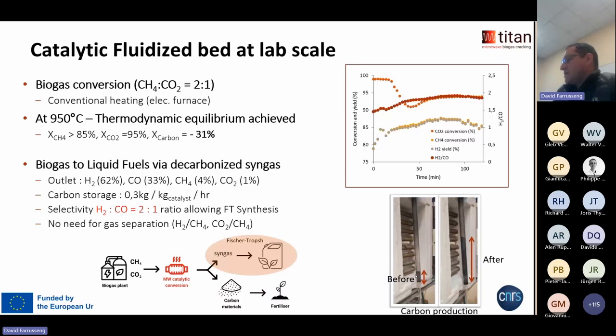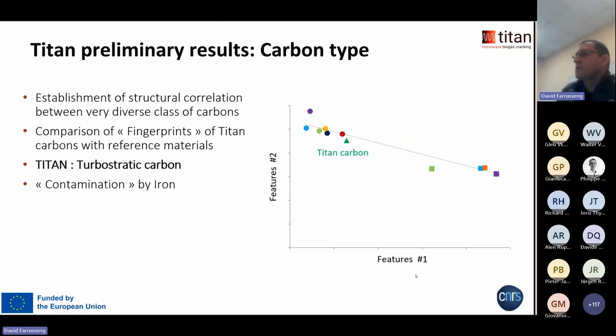You can see the size of the bed before and after 3 hours. So you can see you really produce and store the carbon, while some has been collected on the top of the reactor. And that would mean that with this outlet stream of 2-to-1 ratio, you could think about another catalytic process, namely Fischer-Tropsch, to produce hydrocarbons. So basically, you can think that with only 2 catalytic steps, you could go directly from biogas, of course with some purifications, but I wouldn't say with gas separation, to liquid hydrocarbons you can either use or transport.